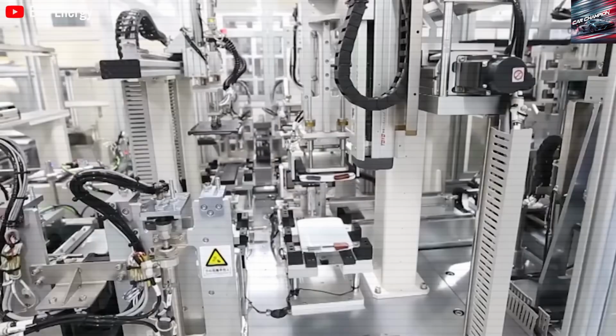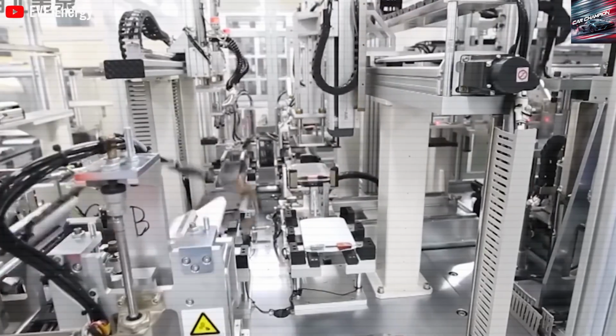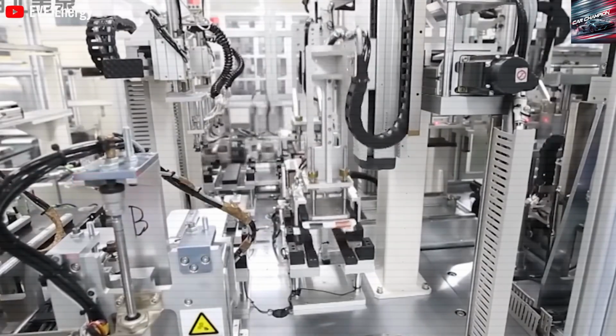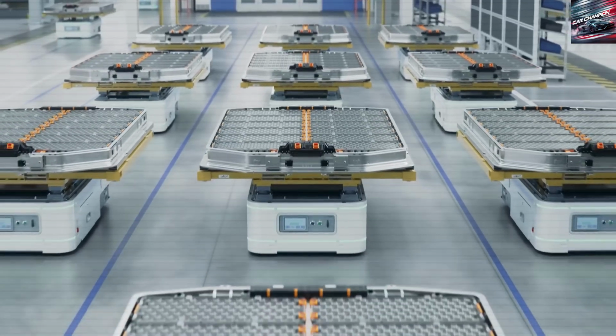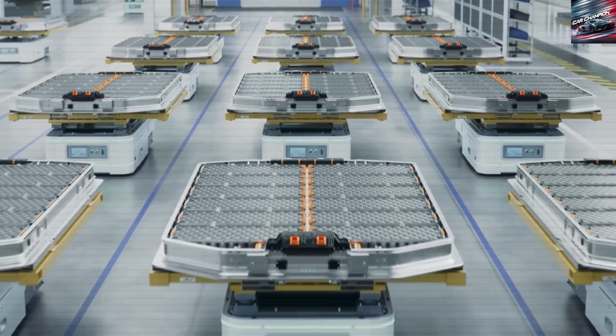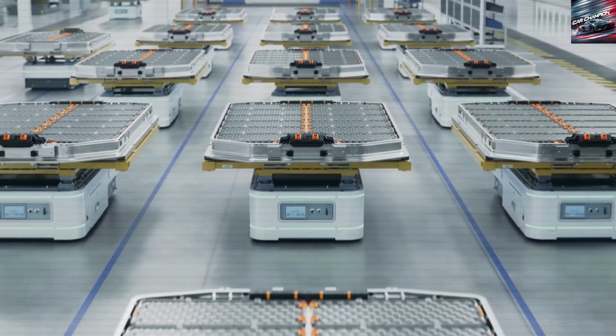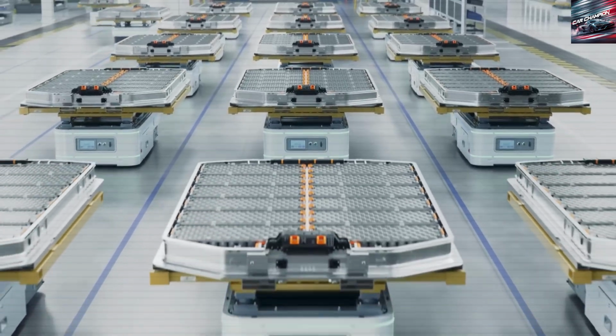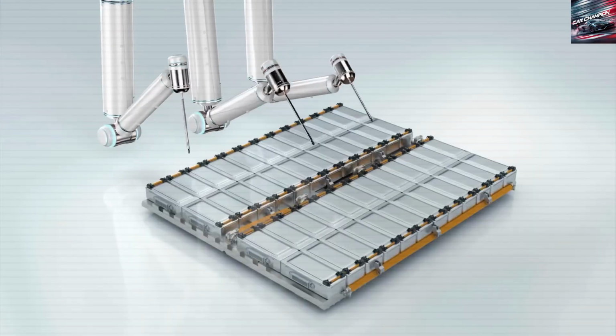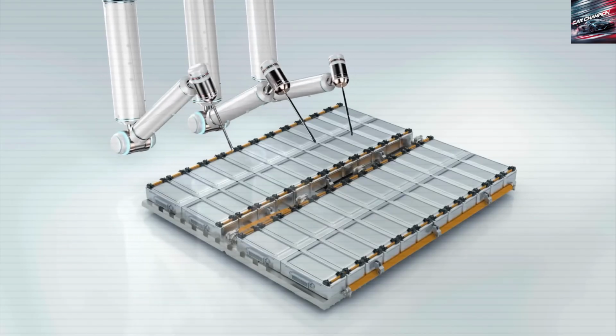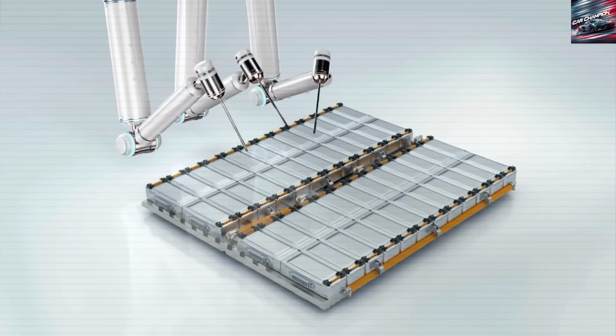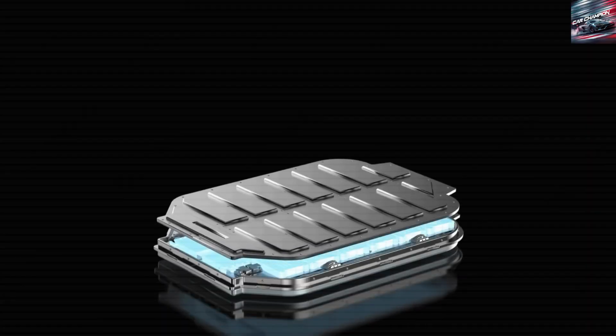Chinese media reports claim impressive performance: 932 miles of range, with just a 12-minute charge from 0 to 80%, and a full charge reaching up to 1,165 miles. These figures, based on China's CLTC standard, are still outstanding. The energy density is 400 watt-hours per kilogram, nearly double the 210 watt-hours per kilogram of average lithium-ion batteries, and much higher than the 160 to 165 watt-hours per kilogram of BYD's Blade battery.